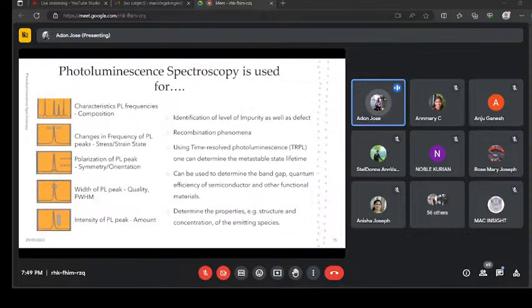The other case is time resolved photoluminescence spectroscopy, which I am going to discuss in an upcoming slide. We can also identify the composition, stress, strain, symmetry from the PL spectrum of a material. How is it possible? Because each material has certain characteristics in its PL frequencies, and based on that we can identify the material's composition. Whereas by observing the frequency variation in PL peaks, we can identify the stress or strain state of that material. And by analyzing the polarization of the PL peak, we can identify the symmetry or orientation of that material.